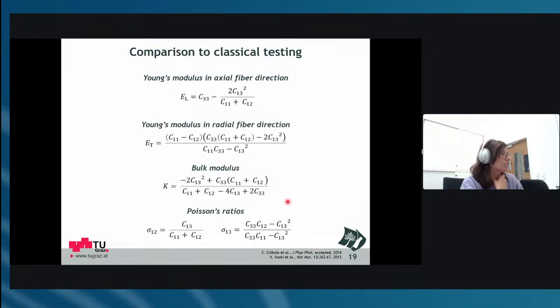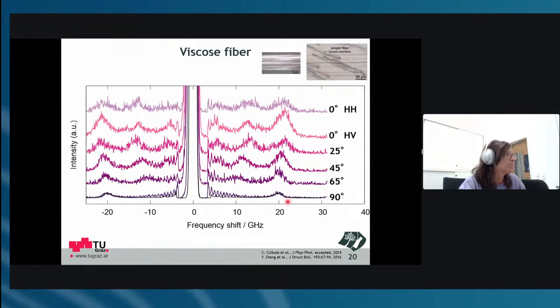Now I will show you some results that we have obtained, and I will show you the results of two different fibers. First, I want to start out with viscose fibers. So this is a very flat fiber. It is several micrometers thick, and it's rather broad. So it's very wide. And I took it because it's just cellulose, and we used it a lot previously in AFM studies to check a few things, kind of a validation material or model system if you want.